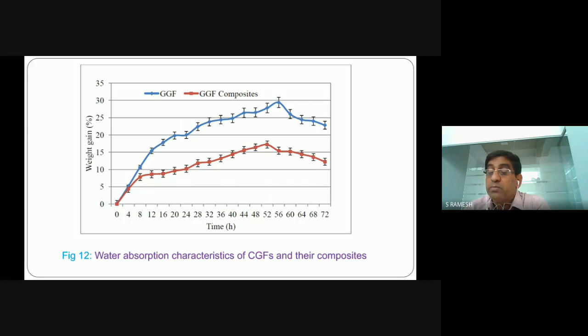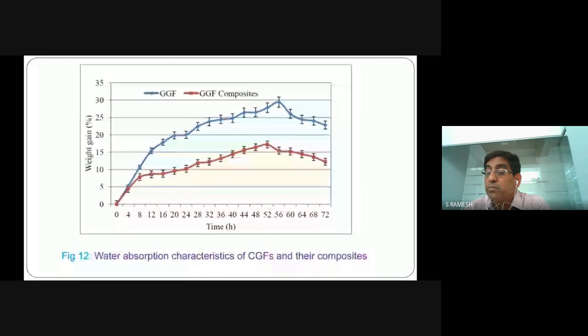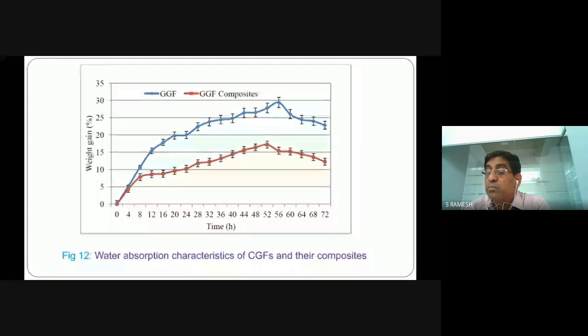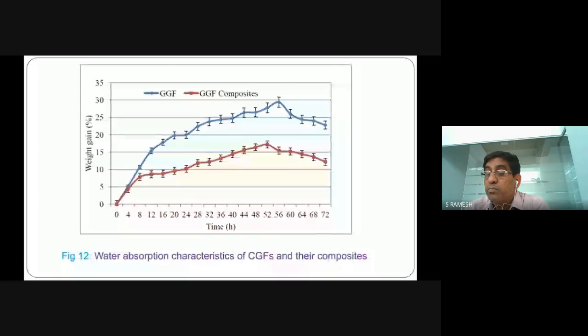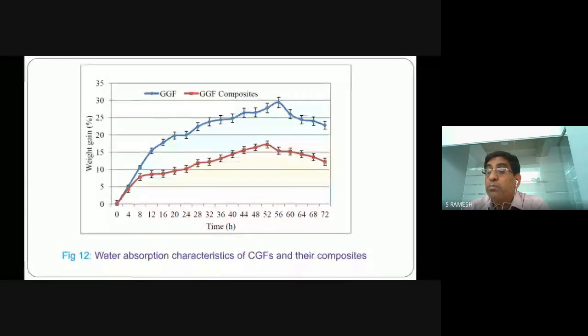For the water absorption test, we take the Calotropis gigantea normal fiber and the composites. If you observe the graph, the Calotropis gigantea fiber absorbs a higher volume fraction of water molecules. The reason is the hydrophilic nature of the fiber. Generally, natural fibers are hydrophilic. Due to that, the fiber absorbed a higher amount of water molecules when compared with the Calotropis gigantea fiber composites.